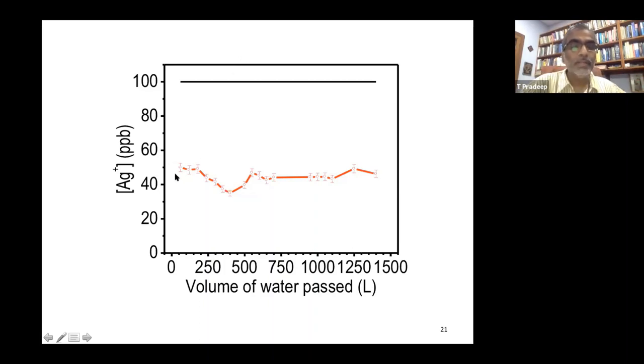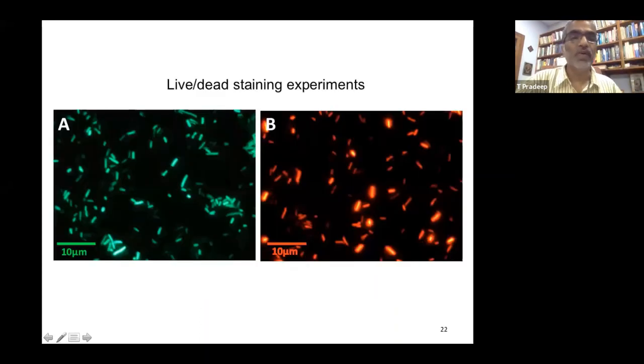But look at this. Because these nanoparticles are embedded in these cages, they continuously release 50 ppb of silver ions. In our laboratory, we don't do 1 liter experiments. We run things for thousands of liters. So here is 1500 liters. Typically these experiments are run for 4000 liters. But what you see is constant. It's drug-like release. This is possible because calcium silicate doesn't go into these nano cages where silver nanoparticles are embedded. Only water goes in and silver ions come out. And this is within the secondary limit for silver ions in water. So this is well within control and you can use it as a disinfectant.